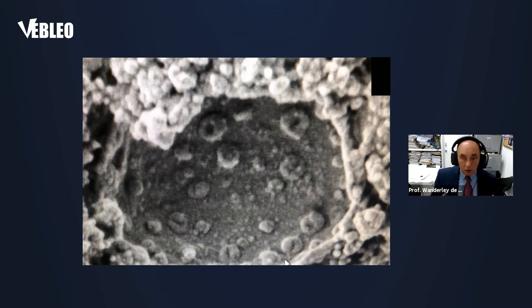If you go on to high resolution microscopy, that I will detail a little more in a few minutes, one new microscope that's called the helium ion microscope, which is a kind of scanning ion microscopy, we can visualize even smaller particles that I am indicating here, that is in the range of 30 to 40 nanometers, that's part of the assembly of the SARS-CoV-2 virus, the virus that causes COVID-19. So this could be visualized by high resolution scanning microscopy.